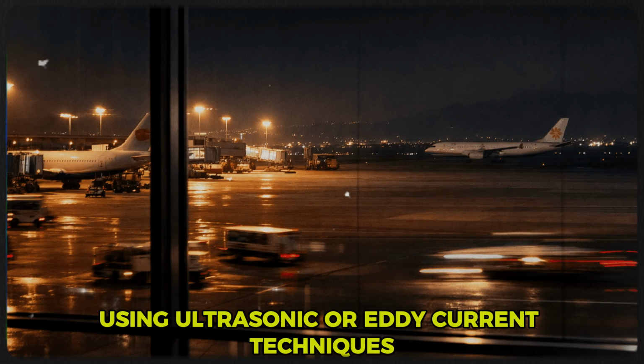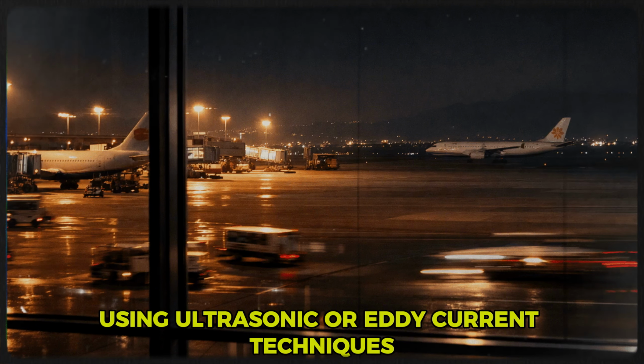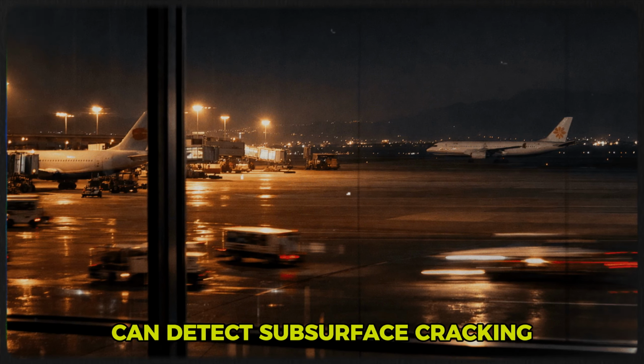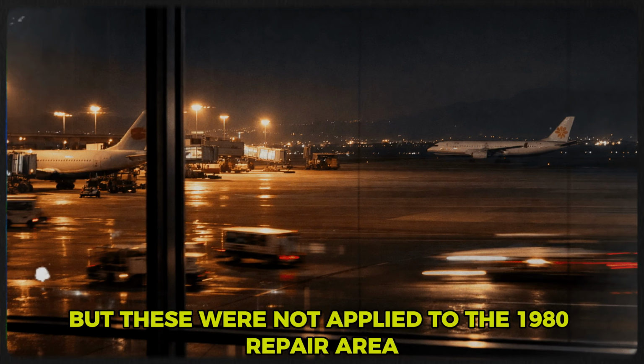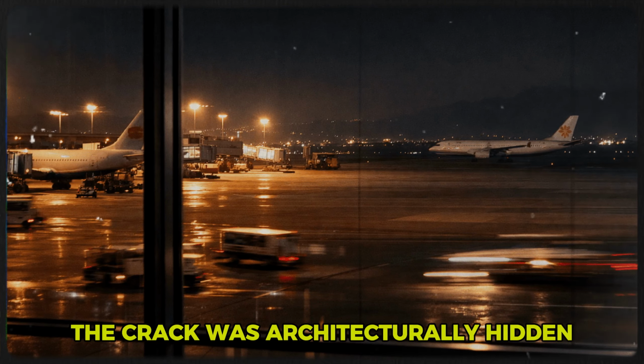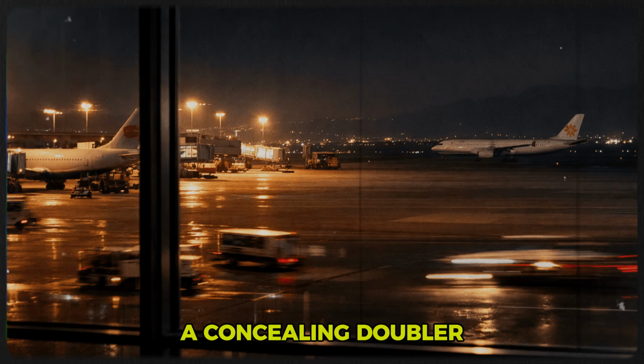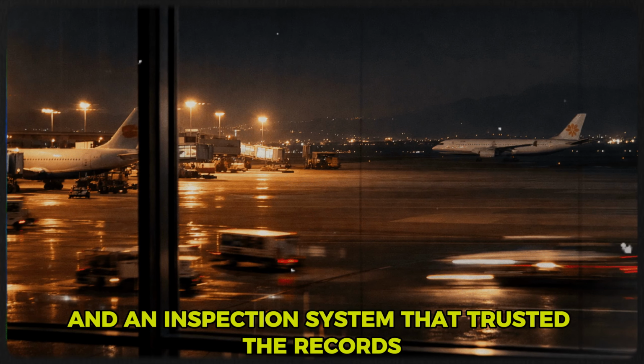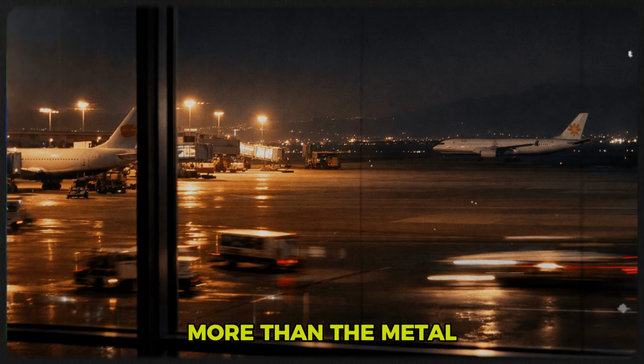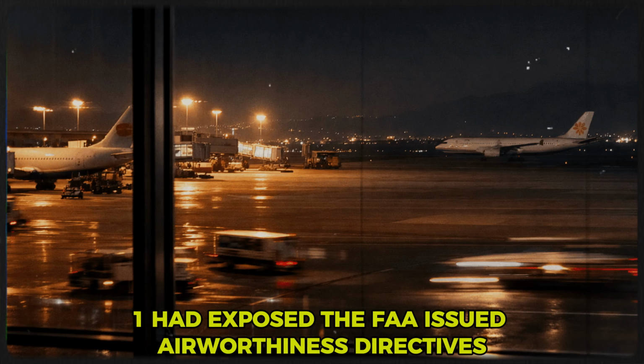Non-destructive inspection using ultrasonic or eddy current techniques can detect subsurface cracking, but these were not applied to the 1980 repair area before the accident. The crack was architecturally hidden, not by intent, but by the interaction of a non-compliant repair, a concealing doubler, and an inspection system that trusted the records more than the metal. The reforms were directed at the systemic vulnerability that Flight 611 had exposed.